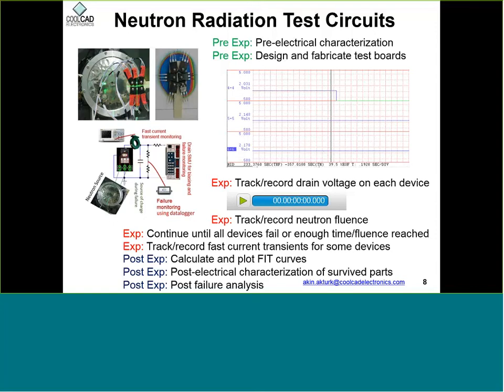So how did we do the test? On the top left, you can see a circular beam output. The beam output is actually behind this circular cylinder, and it is generated by high energy protons hitting a tungsten target, and that creates neutrons among other things, and the other things are filtered out. Then neutrons travel roughly 10 or 12 feet and come out of a hole in the wall, and this is one of them. And then they go through a neutron counter that shows how many neutrons are coming out.